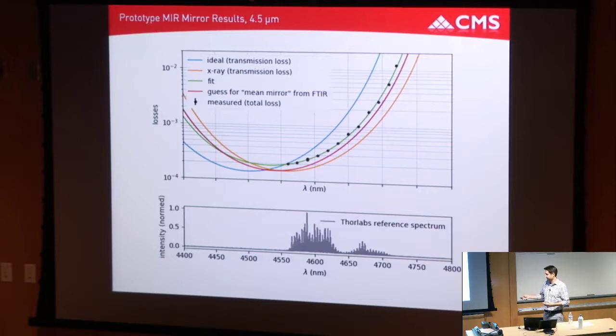So what he did was just feed all of this sort of wide spectrum into the cavity, and then post-selected the wavelength you wanted to measure and ring down on the output side, which was really smart. And then you can select out the finesse as a function of wavelength. And the losses we got down to total losses on the order of 200 parts per million. And in this optic, the transmission is 160 parts per million. So we have scatter plus absorption or excess losses beyond transmission capped at 40 ppm. There's still some parasitic absorption in the path. So we're looking at sub 40 parts per million of excess loss. We're aiming for something like 20 to 30 ppm of excess loss.